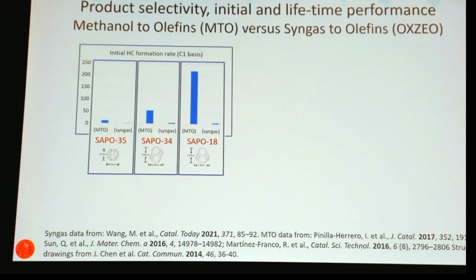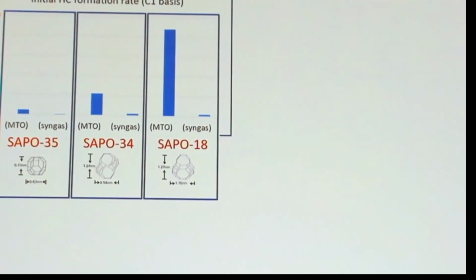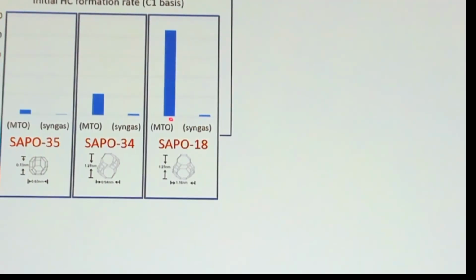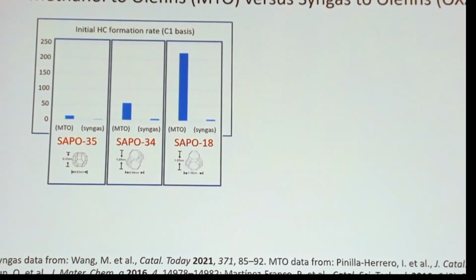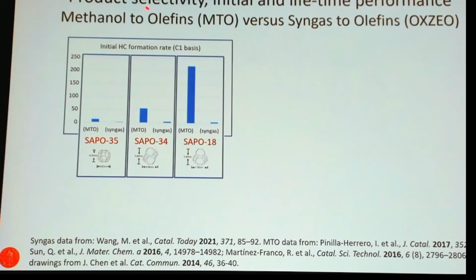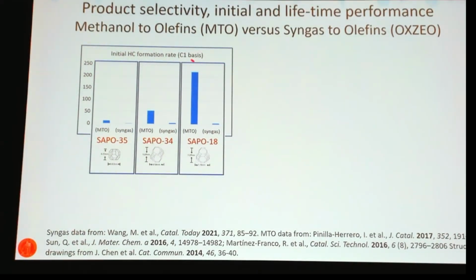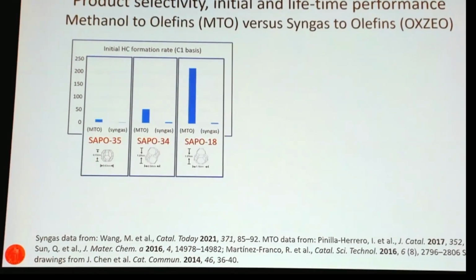Now I took a look in the literature, and I found one study with diluted syngas over 3 zeolites combined with a zinc zirconia methanol catalyst, and then compared it to other MTO studies of the same zeolite types in the literature. So it's not the same studies, it's not the same group, but still we can compare. If we now look at the initial hydrocarbon formation rate of these systems, we see that systematically MTO gives much higher rates of product formation than the syngas process. So we see it's a general feature here that the tandem process has much lower conversion rates.